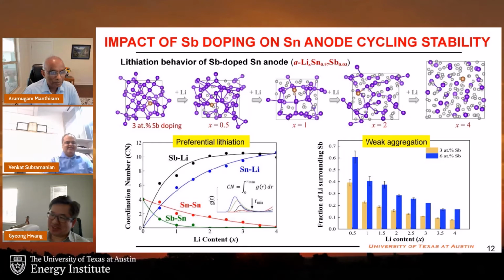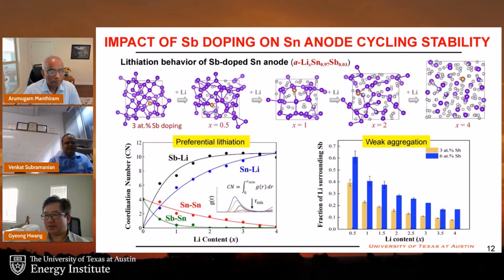So as Ram mentioned, the performance of anode materials tends to be improved by adding a small amount of dopant. So using first principle atomistic simulation, we have examined the doping effect on the lithium behavior of tin and antimony-based anode materials. The top figures show the structural evolution of antimony-doped tin with the lithium at the atomic scale. Here, the dark yellow ball indicates antimony. The gray and the purple balls represent the lithium and the tin atoms, respectively.